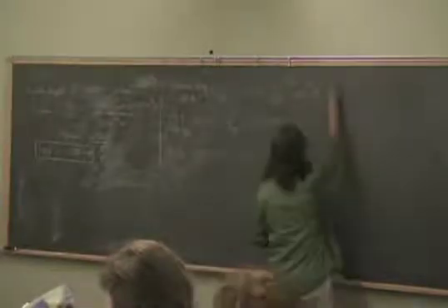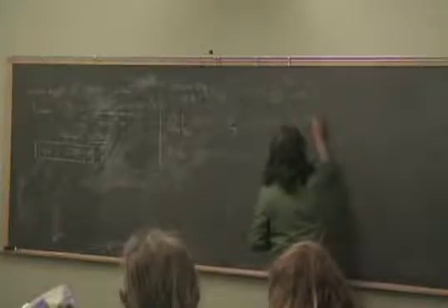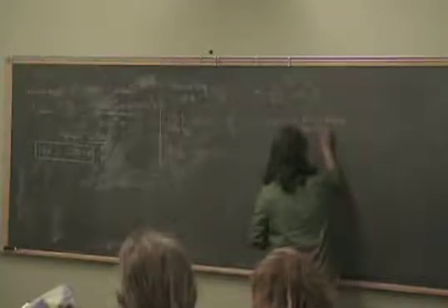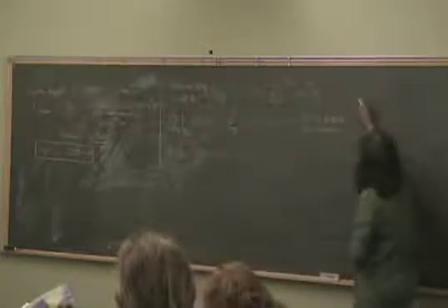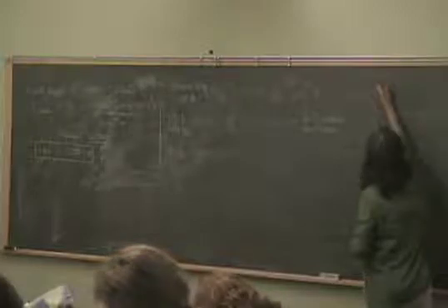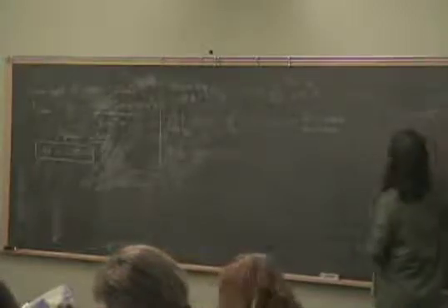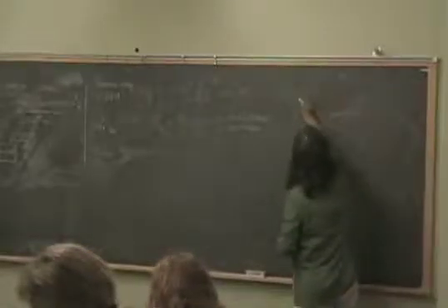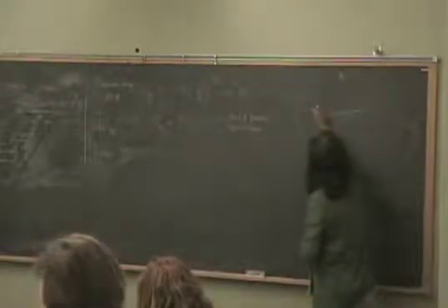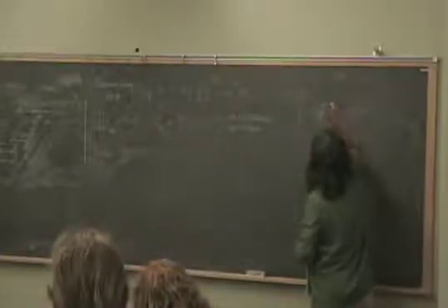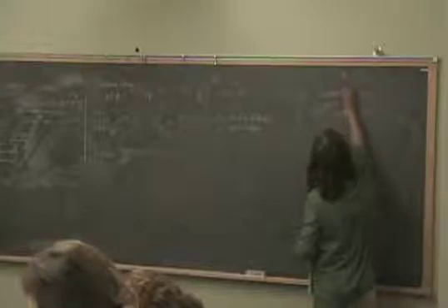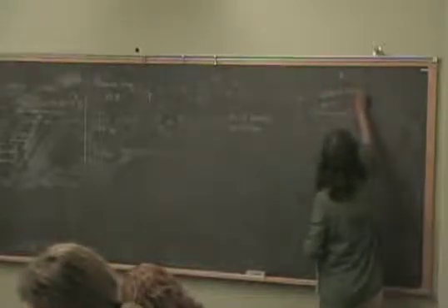So that's the next step. So we have the gold sphere, and this would be, let me write down here, bulk plasma oscillations. Absolutely, if you were to just measure epsilon of omega for gold, it will have some structure of this kind. Okay? This is for gold. It will start out like this, and we will come back to this picture. You will get something at about 2 eV. I'm going to show you some data for that. There will be some interband transition. So I'm giving you some of these answers before discussing it, and I'm going to discuss this in more detail.